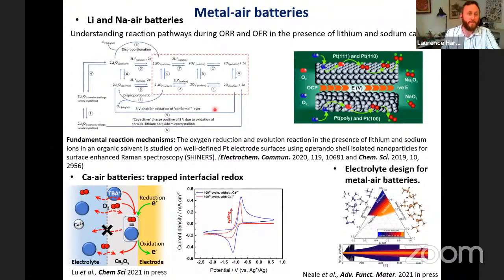And just to wrap up this section, we've done a lot of work looking at single crystals, particularly platinum single crystals, trying to really dig very deep into the reaction mechanisms of oxygen. And we've used SHINERS to look very carefully at the sodium-oxygen system and seen different reaction pathways on different orientations of platinum single crystals.